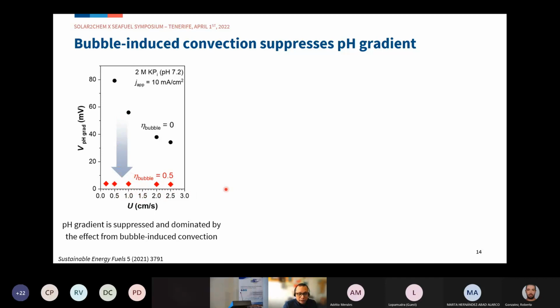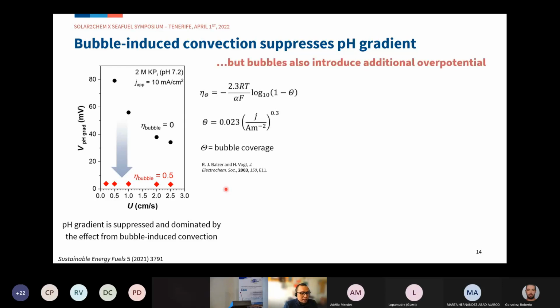So this is a positive aspect from these gas bubbles. However, at the same time, we also need to notice that the bubbles also introduce additional overpotential. One source is due to surface coverage, and one can estimate the surface coverage from this empirical relationship reported by Vogt, and calculate the overpotential caused by this coverage.